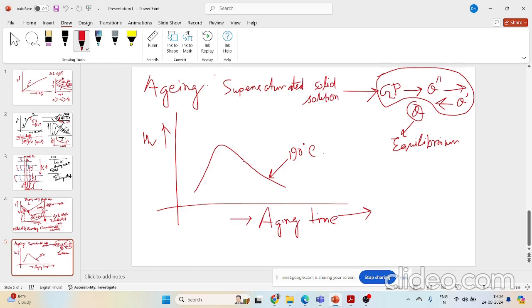somewhere around an aging time of 10 days, formation of theta dash was there, and towards the end, I'll be forming this equilibrium phase. And another temperature region is lower than this. So that will show some characteristics like this. This is at much lower temperature. That was done at 130 degrees.